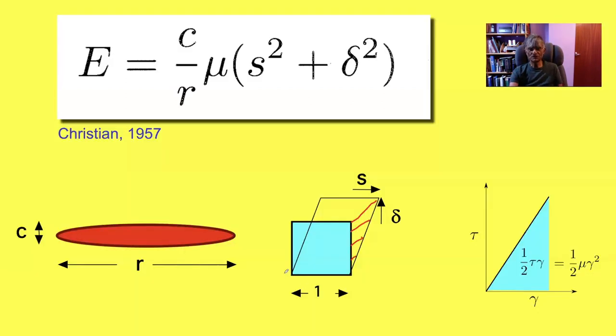So there is a big advantage in making the martensite a thin plate, because if it is shaped like a lens with sharp tips, then the displacement at the tip is very, very small. This helps to minimize the strain energy per unit volume, and therefore martensite is in the form of a thin plate. That's a very important conclusion just by looking at a simple consideration of strain energy per unit volume. Of course, if the martensite becomes even thinner, there would be less strain energy, but you have to think about the fact that we want to achieve transformation. So the actual thickness is determined by balancing the chemical driving force, which is the difference in the free energy between the austenite and the martensite, and the strain energy per unit volume.